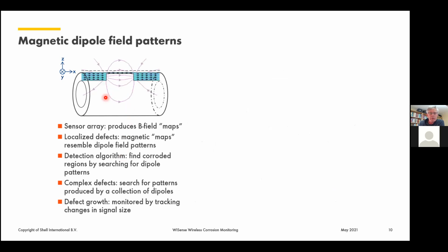So again, magnetic dipole field patterns are excited in the area where the defect is growing. And then the sensors that we put over the pipe are picking up the field, the B, the magnetic induction fields, in so-called maps. I'll explain that later. Our sensors have a square of 12 by 14 sensors in a 6-inch by 6-inch area roughly. That is the standard patch size that we worked with a lot so far. These magnetic maps show the localized defects in terms of a dipole field.